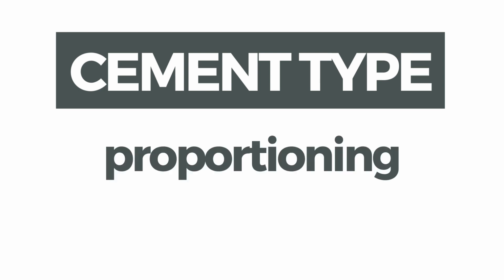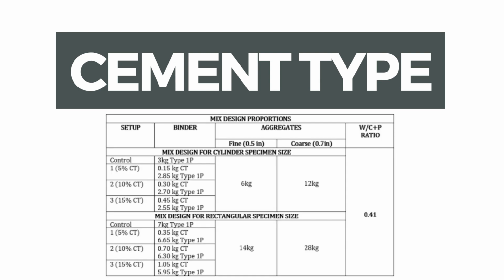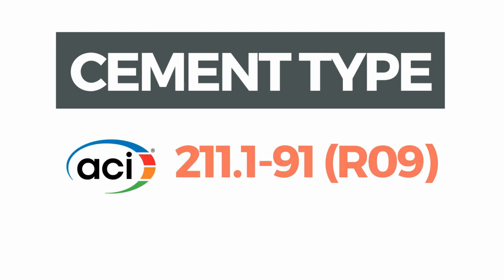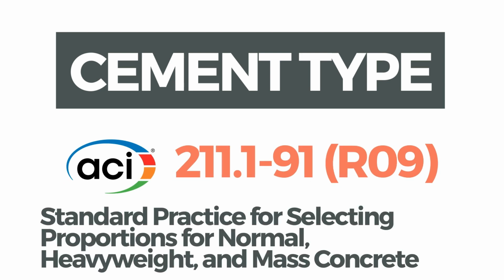Further, proportioning of components other than aggregate binder will be in accordance to ACI 211.1-91 or the standard practice for selecting proportions for normal, heavyweight, and mass concrete. As one might expect, a slump test following ASTM C143 and a water absorption test following ASTM C1585-13 will be conducted in the preparation of the material.